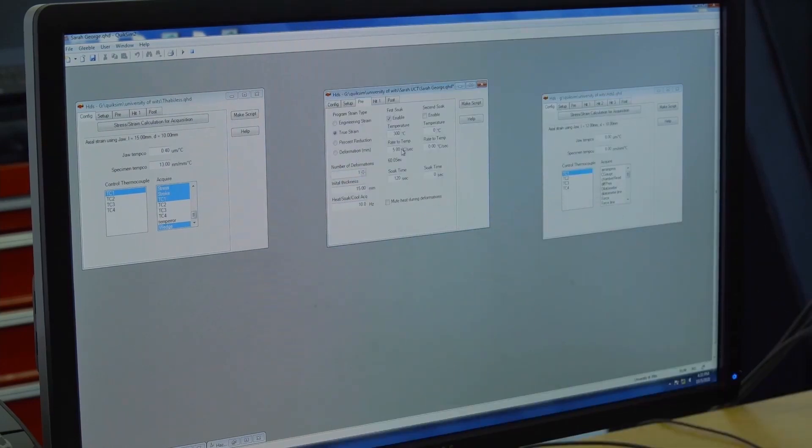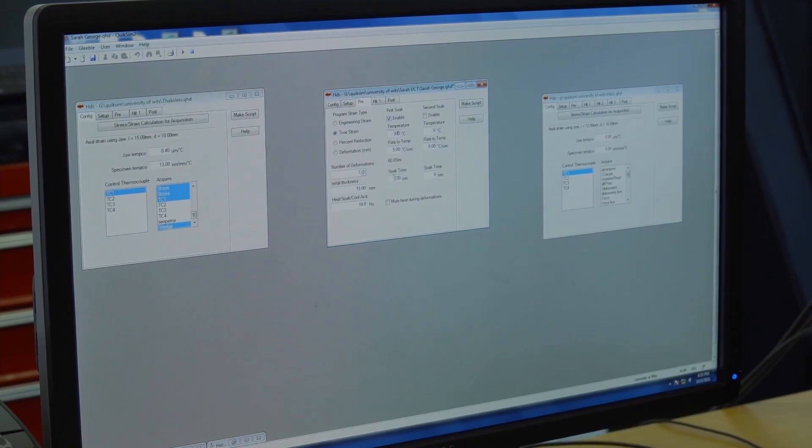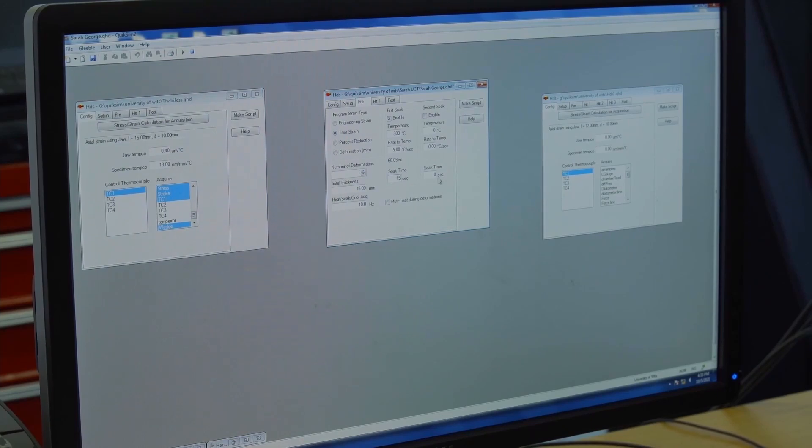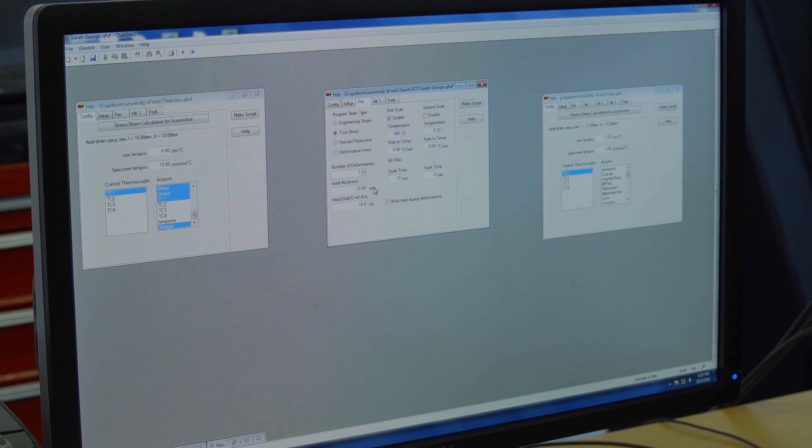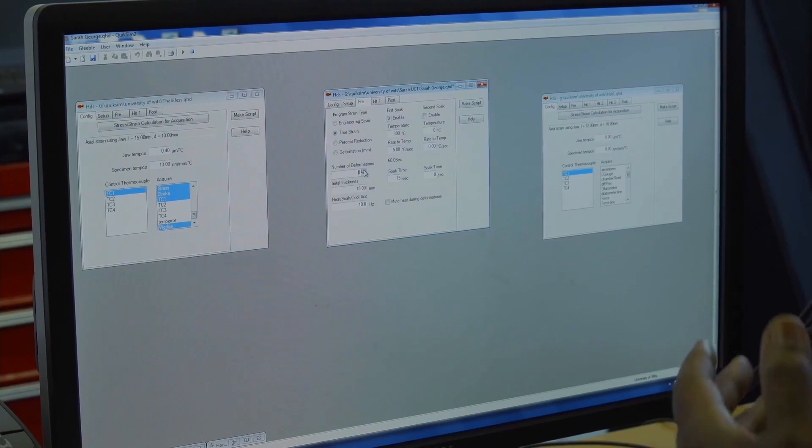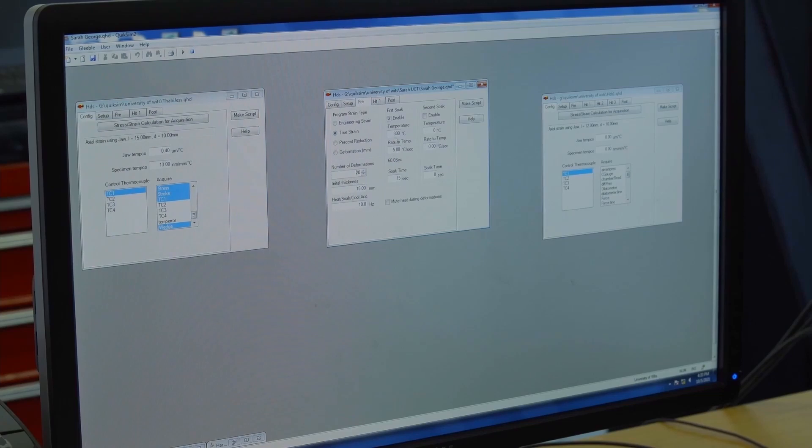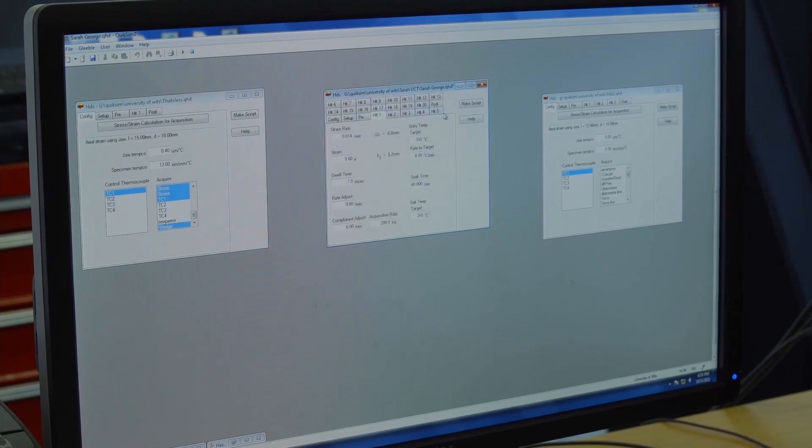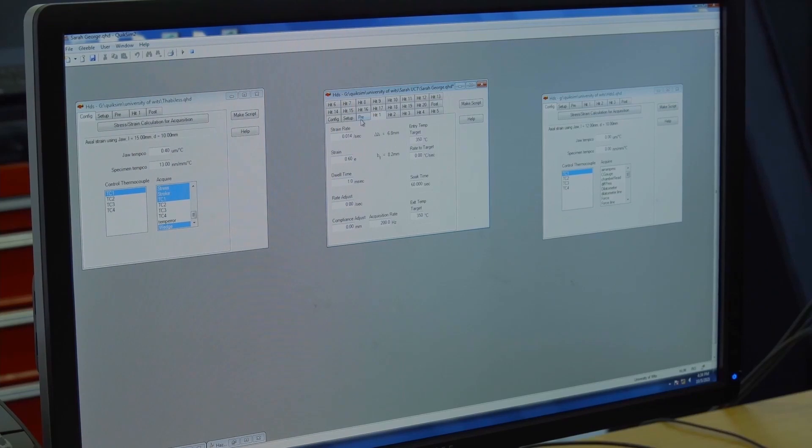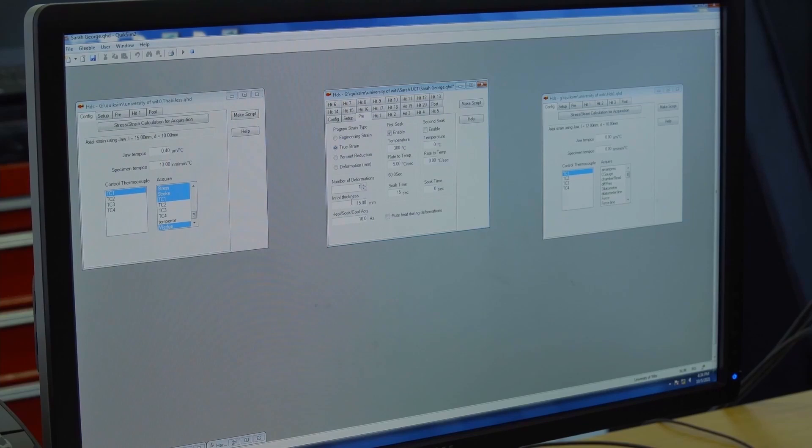Here, the rate at which the Gleeble heats the sample to attain this temperature is 5 degrees Celsius per second. That is the recommended heating rate for the ISO-T anvils that you have on the Gleeble. We want to hold for 30 seconds. If you are simulating rolling operation, you may want to increase this to many heats. You can have up to 20 heats here. We really don't need that because it's just forging that we are simulating, and forging is just one stamp.